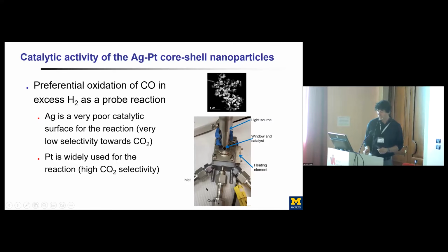Anyways, I have a couple of slides somehow stuck, but essentially what the slides show is that this core shell nanoparticle of platinum silver actually can perform this plasmonic chemistry as we shine light. And what it is telling us is that this energy that's transferred to platinum is actually driving that preferential CO oxidation, and we see enhancements that are relatively significant.